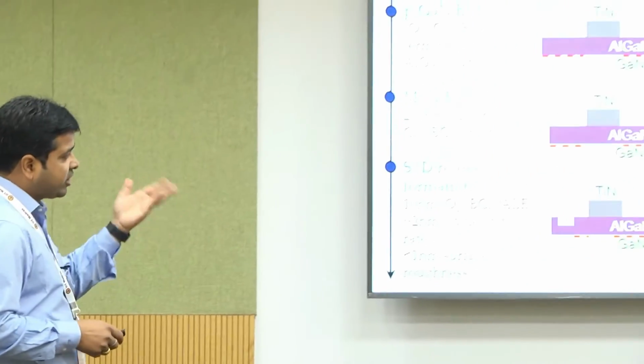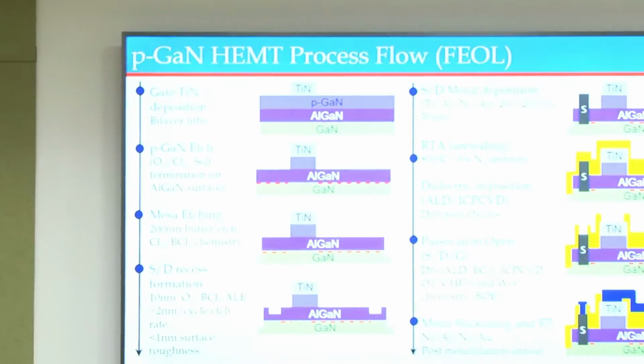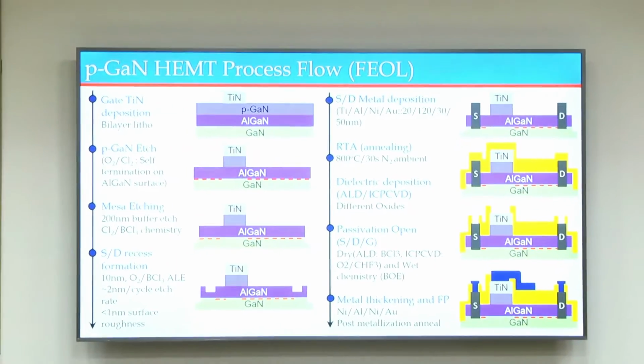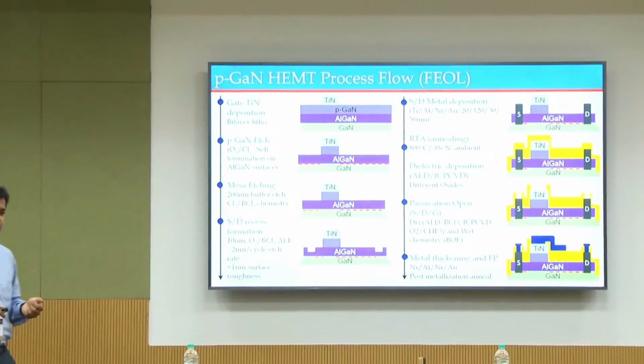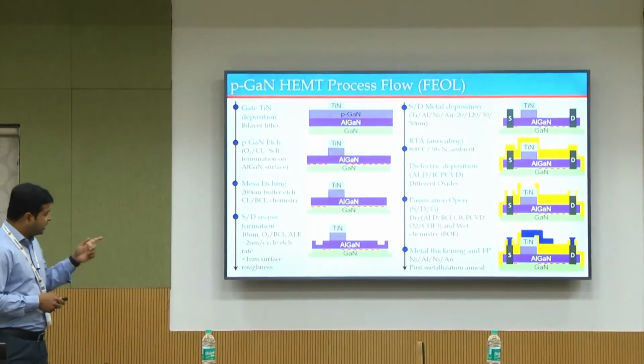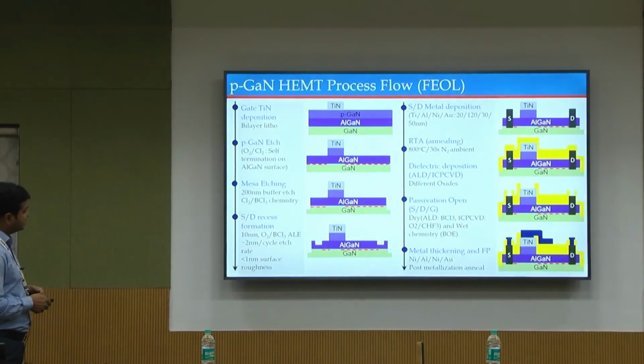We have published a lot of papers on this aspect also, that field plate design has to be done while keeping in mind the stack type, the kind of trap configuration in the buffer, the sheet charge concentration, and the kind of passivation and surface trap configuration over there. So field plate design is also a complex process here. And then since we are talking about high voltage and high current devices, tens of amperes of current, the back end of the line development is also equally challenging, which I'll talk about a little later.